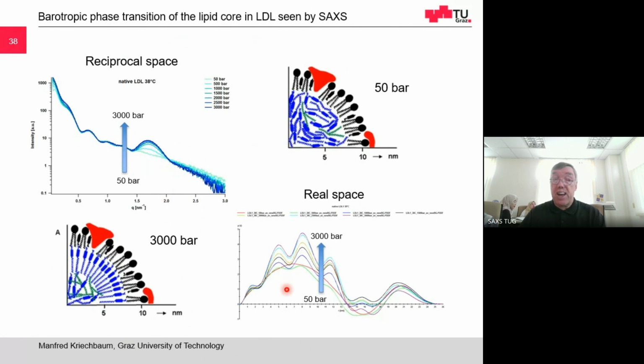If you make the Fourier transformation into real space, you see before you just have a diffuse, no structure, and the higher the pressure, you get this structured, layered structure in the inner core. You can see it immediately here in the p(r) function. So this was high pressure with LDL, but we can also do it with lipid alone or also with protein alone.